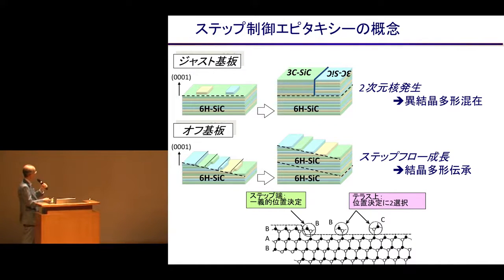So we developed a model for this concept, and for the on-axis, the terrace is very wide. When the terrace is large and the silicon molecule comes, there is a choice, the zig or the zag, and they will grow horizontally and collide. Then it would create the mosaic pattern that we saw a while ago. In the case of off-axis, the structure will be a step structure, and the terrace is small. So for the horizontal side and the vertical side, there will be chemical binding, so there will be a replication. This is actually well known in the crystal growth field, but we are in the device field.